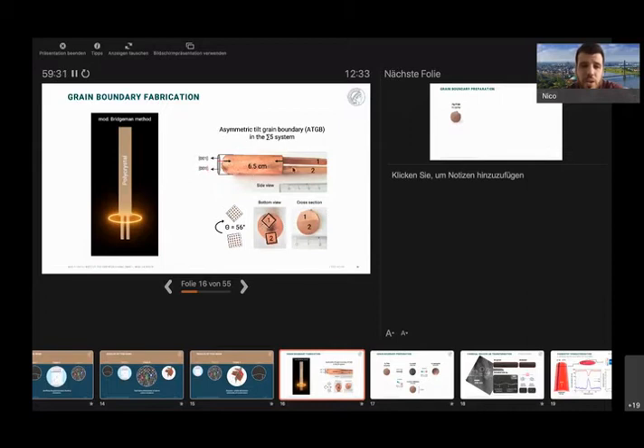And there it often happens that initially you form the boundary because the seed crystals grow, they crystallize, and then they meet. And in the middle, of course, they meet, where else? But then growing it further, they just run out towards the side. And this is probably related to different surface energies of the two different crystals that we use or whatever.